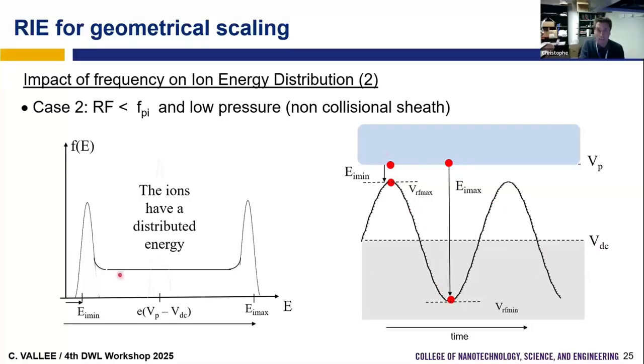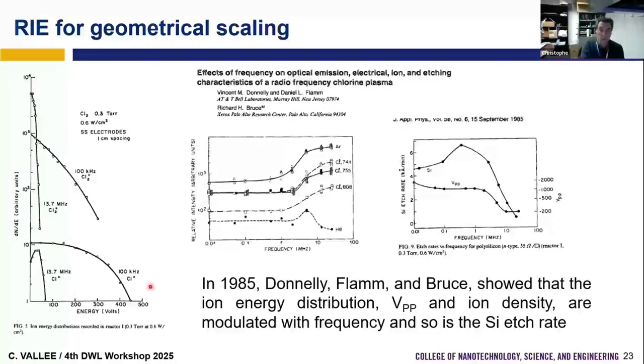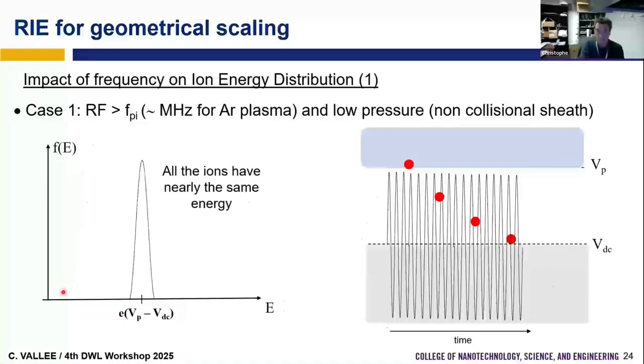And so we now have a broad distribution of the ion energy because they can come from the minimum energy to the maximum energy, and they can take all the energy in between. So the energy of the ions can be much higher than the energy of the ions with a high frequency generator. So this is what we obtain: high energy and large distribution for low frequency, low energy and narrow distribution for high frequency.